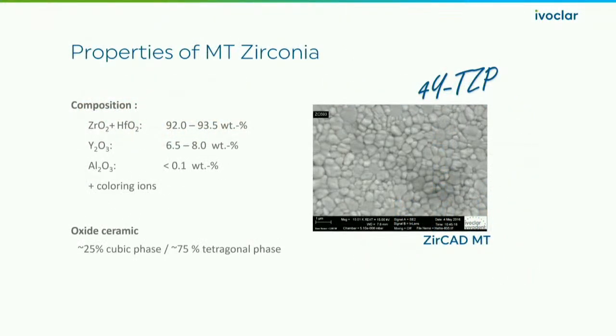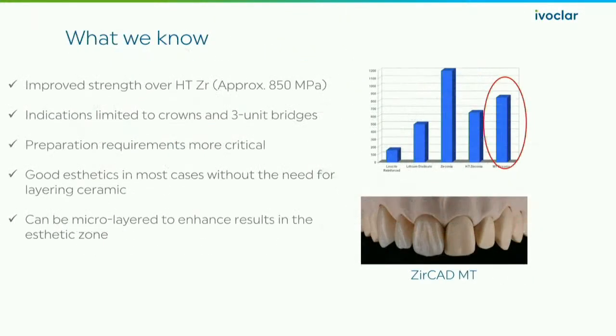And that's kind of what the grain structure looks like. The strength over the HT is about 850, like I said, 600 to 650 for the 5Y materials. Limited to 3-unit bridges. We're in pretty much the e.max press or CAD indication range as far as single units and bridges go, except you can incorporate a molar as a pontic or a molar as the abutment here. Preparations are a little bit more critical in that you're looking more towards that all-ceramic deep chamfer or shoulder.